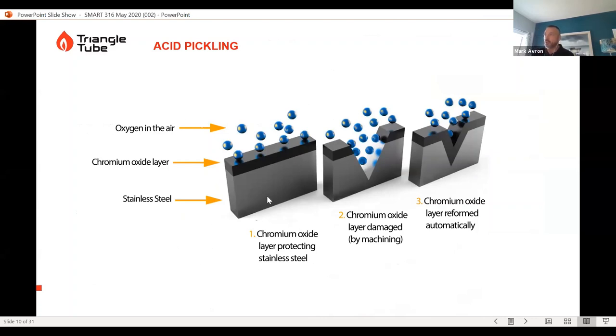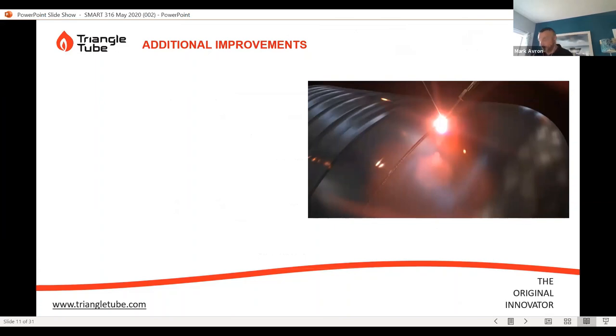Here's another way to look at this. The image on the left-hand side shows your stainless steel on the bottom, and then this naturally occurring chromium oxide layer is a protective layer against oxygen corroding the stainless steel. When you start to cut and weld the material, you expose that bare stainless material and take away that outer chromium oxide layer. Getting back to the last picture on the right, after we've machined and manufactured the material, using this acid pickling process we can restore that naturally forming protective chromium oxide layer. So it's not just the material you're using, it's also the manufacturing processes that you're using here.